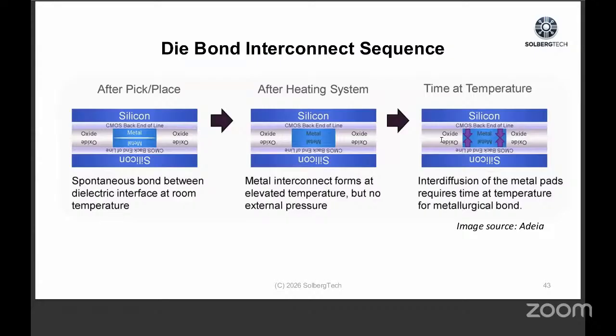So here's the step-by-step furnished by Adeia. On the left side, you see the first step is to bring the two elements together. Let's say the silicon item on one side, and in this case it's showing silicon, but it could be the glass interposer on the other. And you see there's a slight air gap between the metallizations there. What initially happens is the polymer material comes together first, and then it goes through an interconnect.